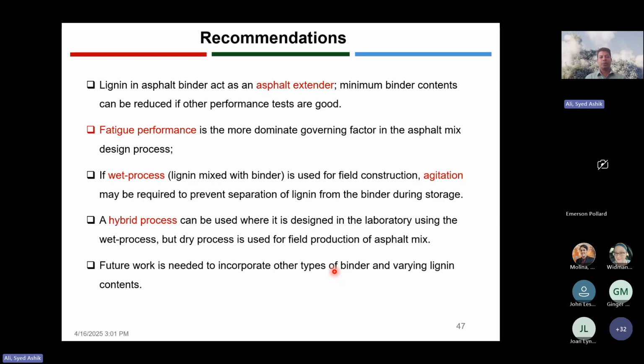If we use lignin in a wet process, maybe during field construction, we have to have a mechanism to agitate the blended asphalt mix or modified asphalt binder, so that we have a uniform mix just before we mix it with our aggregate.